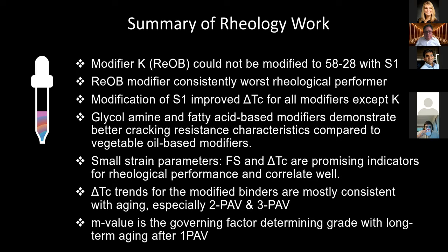Small strain parameters such as frequency sweep and delta Tc are promising indicators for rheological performance and correlate very well. Delta Tc trends for the modified binders are mostly consistent with aging, especially once you get into the 2 and 3 PAV aging. Again, as the graphic showed before, the m-value is the governing factor determining the grade with long-term aging after single PAV.